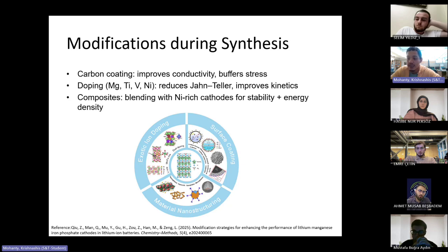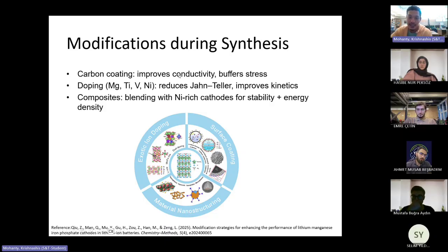So the carbon source is added into the material as a precursor, and because of that, we have an amorphous carbon coating for each and every LMFP particle, which again improves conductivity because carbon is not in olivine form; it does not have a structure. So electrons use this carbon as a way to conduct themselves through the structure itself. So carbon helps conductivity by providing this path, and it also buffers stress because the structure does not have to do much load in storing and transferring lithium because carbon does it for the structure itself.